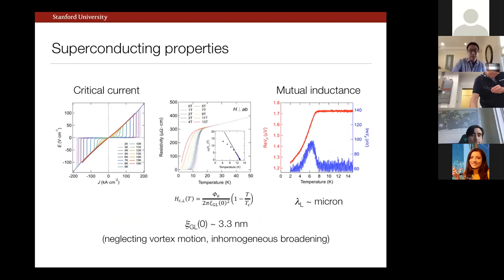So looking at the basic superconducting properties, even though this is a rather unusual and difficult to stabilize phase, even our first experiment showed that it was fairly robust, namely that the critical current densities were approaching 200 kiloamps per centimeter squared. Now we, in some cases, can get up to 350 or so. So this is a non-trivial fraction of what you would see in, say, cuprates. And so quite a robust critical current. If we look at the magnetoresistance, this is for the perpendicular magnetic field orientation, you can nicely see the suppression of TC, and you can extrapolate out a Ginzburg-Landau superconducting coherence length of about 3 or 4 nanometers, sample to sample.